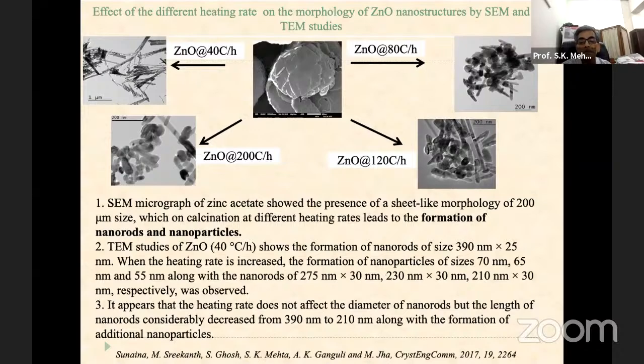So it seems that the heating rate does not affect the diameter of the nanorods, but the length of the nanorods considerably decreased from 390 nanometer to 210 nanometer, along with the formation of additional nanoparticles. This was the conclusion which was made. So this is an interesting study to understand how zinc oxide particles behave.